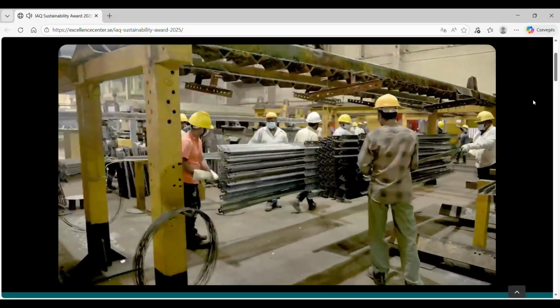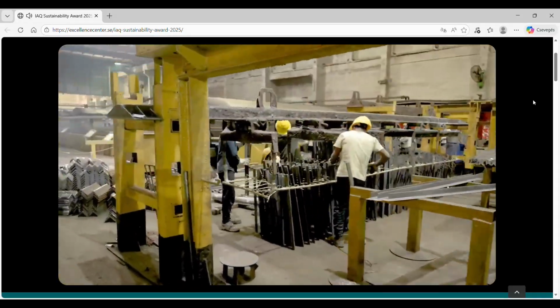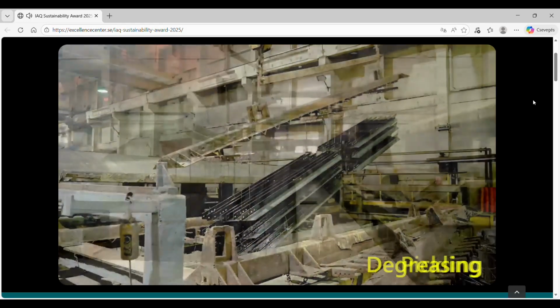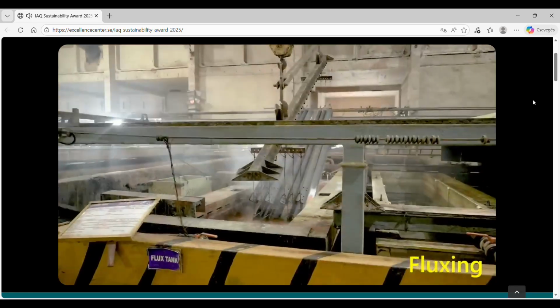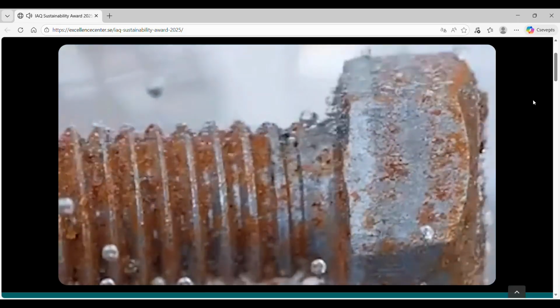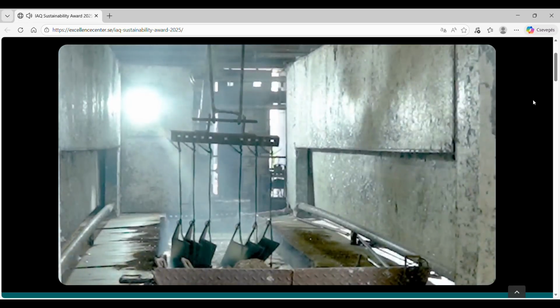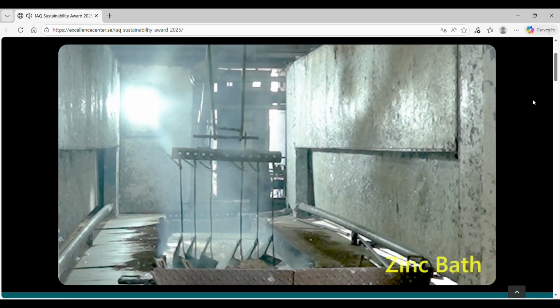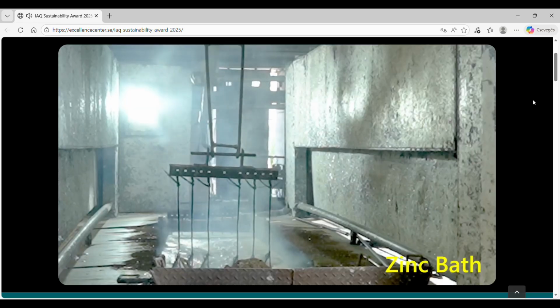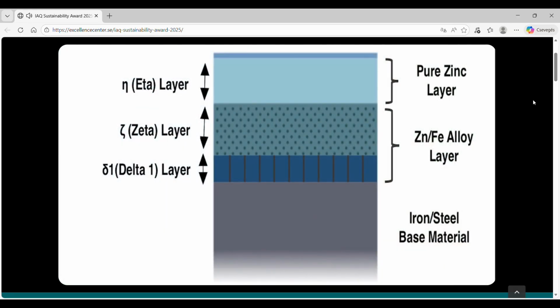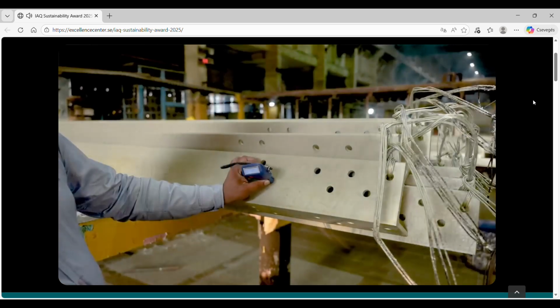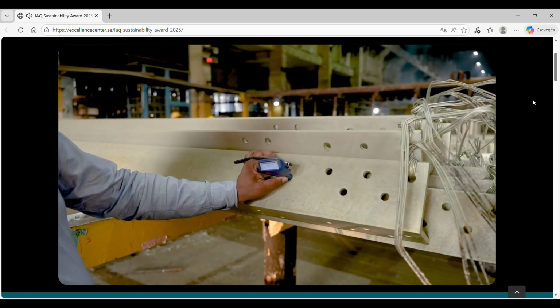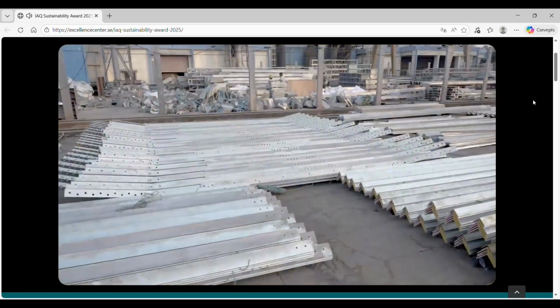The galvanizing process begins with surface preparation. Steel passes through degreasing, pickling, rinsing, and fluxing, removing oil, rust, and impurities to ensure strong adhesion. Next, the clean steel is immersed in molten zinc at 450 degrees Celsius. A metallurgical bond forms, creating a corrosion-resistant layer. Even if scratched, zinc protects steel through sacrificial corrosion, extending its service life for decades.